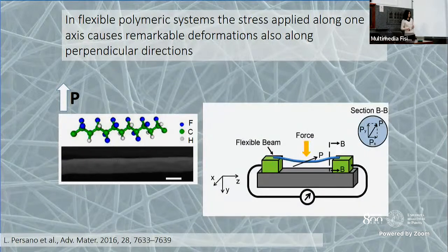And this is the reason why, in order to rationalize this behavior, our case study was to make a nanofiber, suspend these nanofibers with two edges fixed, and it is free to vibrate and oscillate in the vertical direction. And we argued that if we apply the force perpendicular to the main length of the fiber in this direction, we can get a polarization in the plane orthogonal to the applied force. So the transverse contribution to piezoelectricity in these materials can be very important.